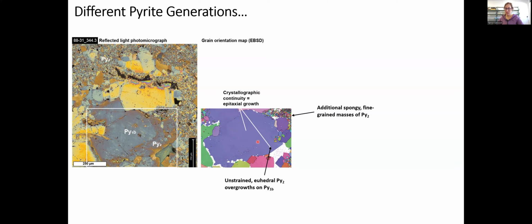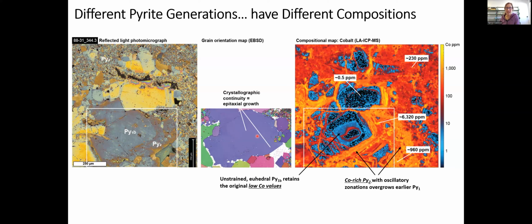In the EBSD, you can't see any difference. They're in perfect crystallographic continuity. So it looks like our second generation just epitaxially overgrew our older pyrite. But where you can see a difference is in the composition. This is our cobalt map, and it really stands out. You've got pyrite 1B in the core, really low cobalt, and that new pyrite that's overgrowing it, very high cobalt, several thousand ppm. So I'm calling that pyrite 2. It's definitely a later generation of cobalt-rich pyrite.